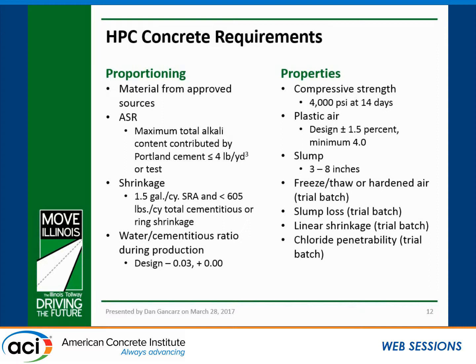We evaluate freeze-thaw or hardened air during the trial batch process. We evaluate slump loss during the trial batch process, and that's one of the tests we have to look at workability. It's one of the things we look at to prove that these mixes can be placed and finished in an ample amount of time. Linear shrinkage is done during the trial batch process, and then also chloride